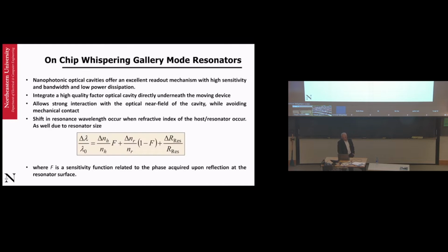So these resonators, essentially these cavities, give us the possibility of sensing. How? Well, if the refractive index of the glass changes for any reason, then you will have a change in the resonance frequency. It will change the condition of resonance, right? Or for some reason, if you could change the dimension of the glass, just like by heating, thermal expansion, that will change the resonance condition. And so those are two quick ideas by which you can start thinking about sensors.